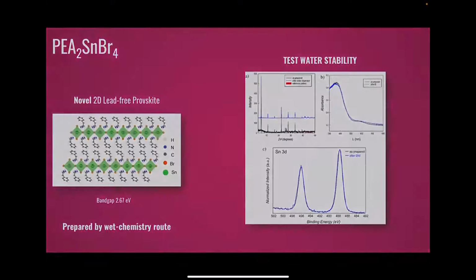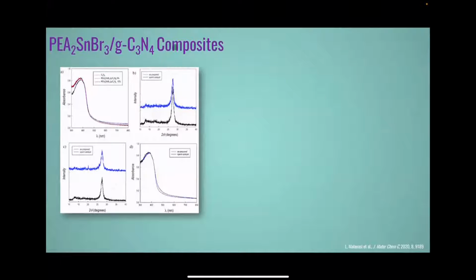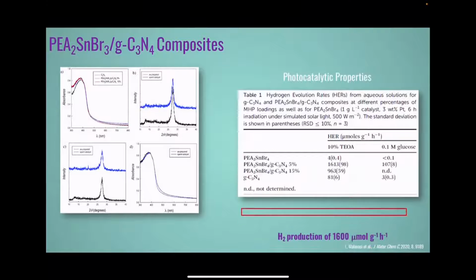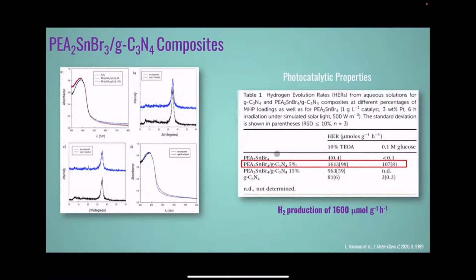Okay, so again we prepare composites, so heterostructures, by combining this perovskite with graphitic carbon nitride, again because the band gaps are similar, so we may expect a good band alignment, so a positive charge transfer between the two. And as a matter of fact, this is another recent paper. If you look at the hydrogen evolution rate of the pure perovskite, about 4 micromoles of hydrogen, of the pure graphitic carbon nitride under the same condition, 81. The composite with 5% of perovskite goes up to 1,600. So another very good synergy between the two materials in creating the heterostructure.